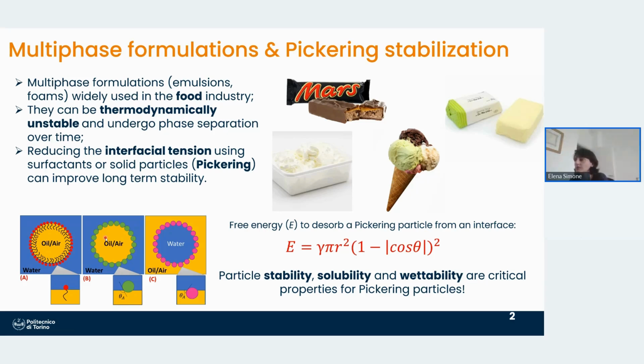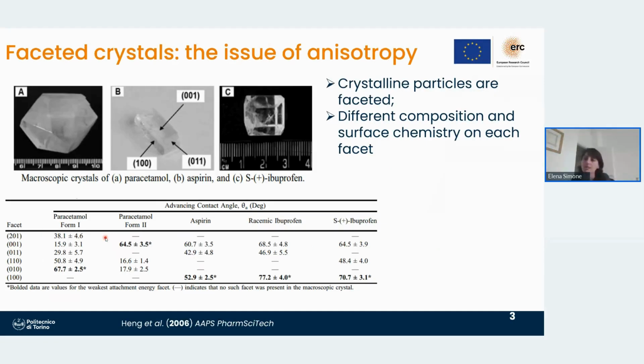Also, what we need to take into account is the thermodynamic stability of our particles. They have to be thermodynamically stable in the formulation, and also they have to be insoluble, so they shouldn't dissolve in either of the phases. Now, we can use crystalline particles as Pickering stabilizers, and crystalline particles are faceted, so they are characterized by an intrinsic anisotropy, which depends on the crystal structure. So depending on the crystal structure, we will have different parts of the atoms or the molecules on each different facet. So we will have different surface, different chemical nature and different wettability, hydrophilicity or hydrophobicity on the different facets.